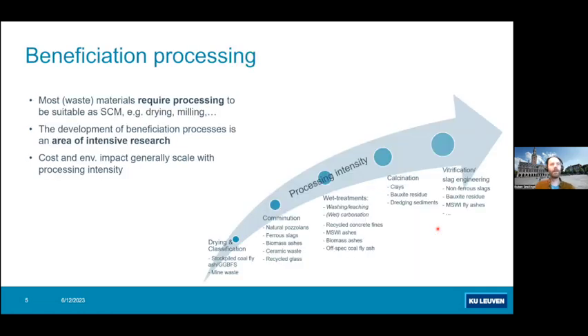An important point to make as well is that many of these materials require processing. We call that beneficiation processing. So from a waste material or from a low value material, we process it and we make it a suitable SCM. And in particular, this seems to be an area of intensive research. Many researchers are looking into ways to upgrade or upcycle, let's say, ashes or slags of some sorts, or even recycled concrete fines. And it's actually in the combination of the processing and then the properties of the end product that most innovation is happening today.